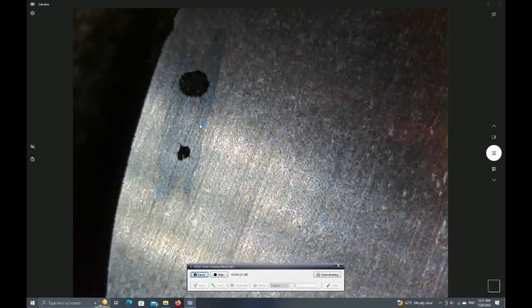And you see some coloration, and I do not think that that's attributed to the camera. I think that's actual coloration. Both ingots were etched with a solution called nital, N-I-T-A-L, which is a mixture of ethanol and concentrated nitric acid, such that the concentration of nitric acid is 3.5%, and then the balance is ethanol. I made that solution at work because I don't have access to nitric acid at home. But anyhow, really didn't take much.